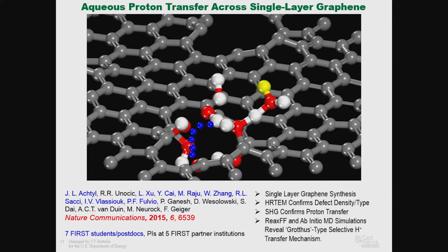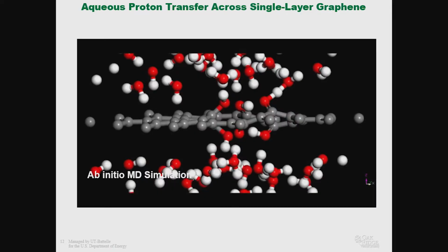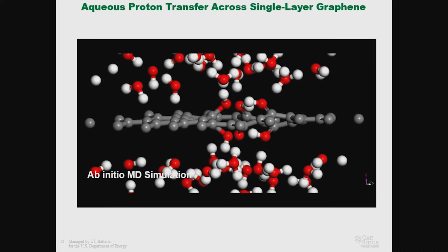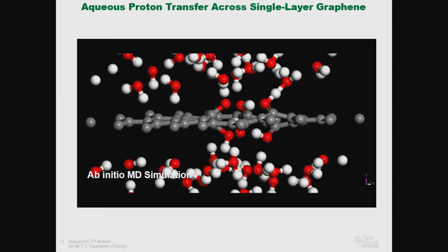The mechanism involves passing protons from a hydronium ion in solution to a surface hydroxyl group. There are three hydroxyls above the defect and three hydroxyls below the defect. I'll show you a movie of the Grotthuss mechanism process that was identified as the way protons shuttle among these hydroxyls and then eventually pass through the pore to the solution underneath.